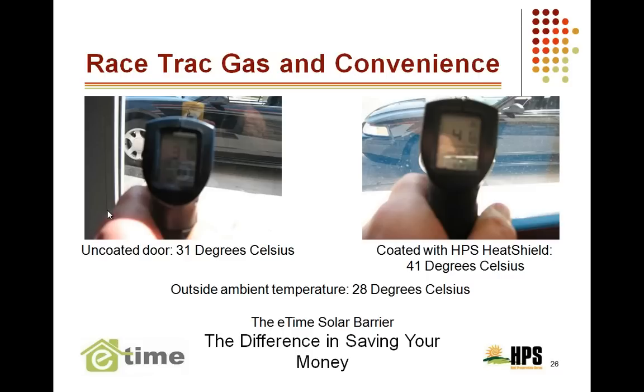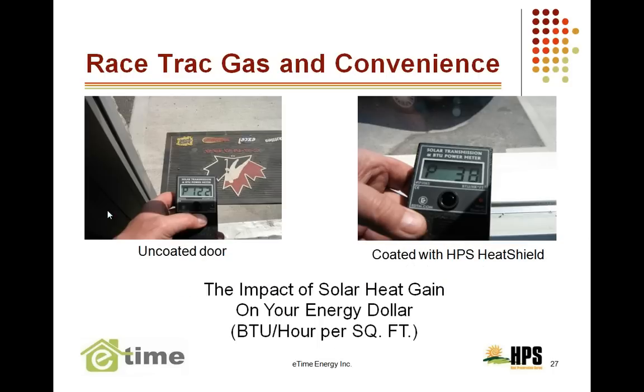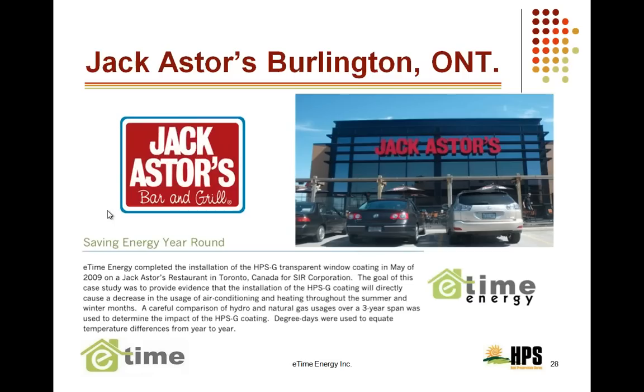The difference in the temperature is about 10 degrees, as you can see, between coated and uncoated. And the solar impact on this window was 122 versus 38. So it's a very dramatic difference between the two. As you can see, it stopped the effects and also lessened his cooling requirements.